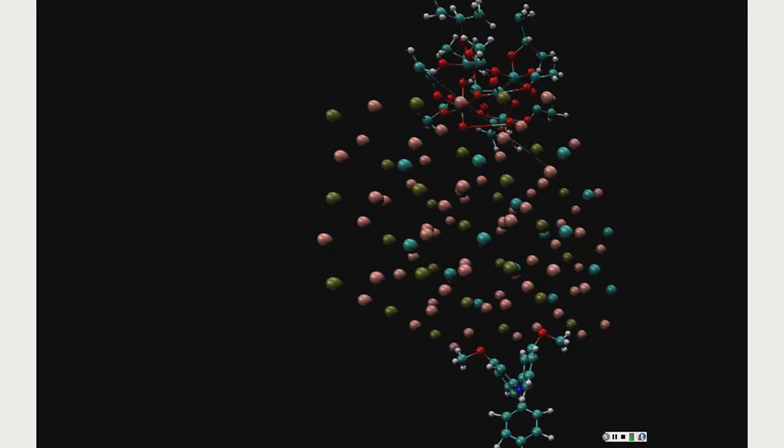So it means you should not really add any energy to the soft atoms at those conditions, because they can get only this quantized energy, not in the classical way. But because you treat them equally, it probably oversaturates the energy. The real energy which your organic molecules get is not really 300 K. If you recalculate, it would be much bigger, and that actually causes the breaking of the bonds. So the practical question: can we do something about this?